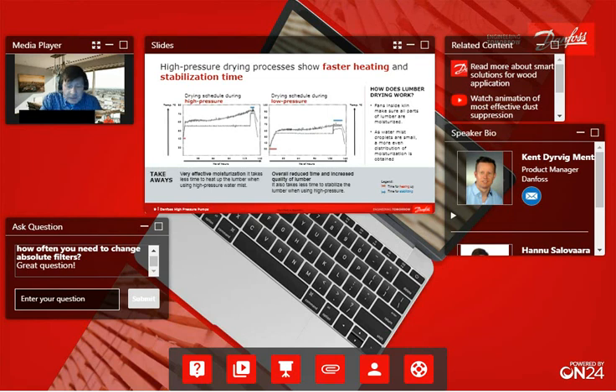Then we have these horizontal lines between the red and blue one. This is a drying process. These curves are wet and dry temperatures, and you can see also that the high pressure model is faster than the low pressure model.